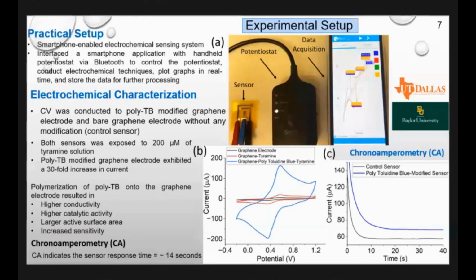We are using this smartphone-enabled electrochemical sensing system. The system is connected with Bluetooth to the smartphone, so you can have all these results on your smartphone, and this data can be extracted out and you can just plot it. Once you look at this graph, it shows the current and the potential, so typical cyclic voltammetry. The black color right here is the graphene electrode. Once it is functionalized, this is what you see in cyclic voltammetry. And once you put the tyramine there, it is right here in red color.